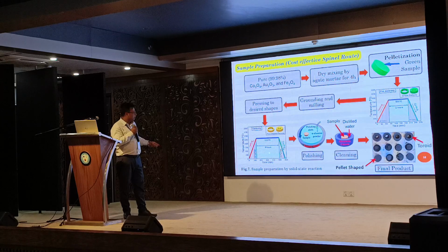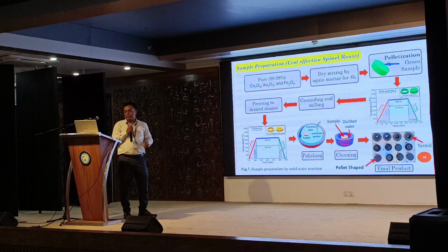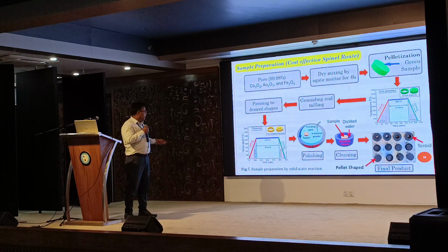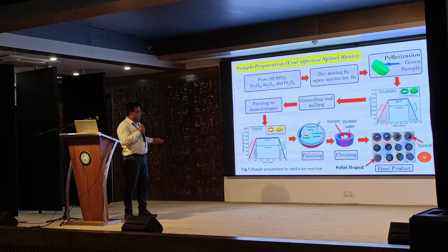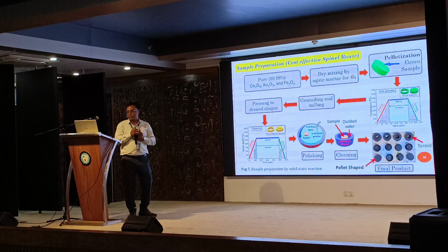Holding time is 6 hours. Heating rate is 15 degrees Celsius per minute, and the final temperature needs actually higher temperature for this method, solid state reaction. That is 1332 degrees Celsius. And after polishing and cleaning by ultrasonic bath, we got this type of materials.